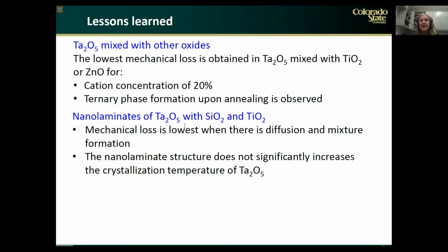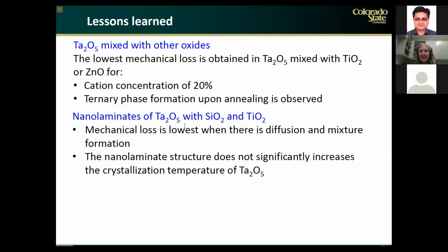So this is what I wanted to present. These studies have shown us that essentially for reducing mechanical loss, we need to get an arrangement in which we form this mixture. And these results are confirmed both from our studies of mixtures and also from nanolaminates. Now, the ideal cation concentration for adding titania or zinc oxide, for example, is of the order of 20%, which is exactly what has been determined in titania doped tantala before.